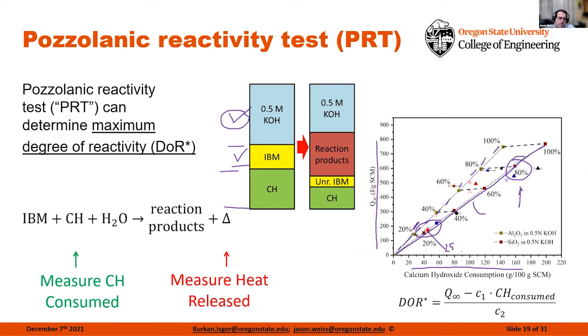There are lots of people who want to say, well, it's about the amorphous or glass content. This, for example, where you fall on this graph, and we've shown this before, is a great indicator of your glass or amorphous content. There's lots of other people who want to say, well, what if you have some calcium? We've got equations that account for these. And in fact, in January in Concrete International, we're going to have an article that really says you could greatly simplify a lot of the testing that we do for fly ashes simply by measuring the heat and using a graph like we see on the right-hand side. So this is something we believe in very strongly. We've presented it to ASTM. If they want to move it forward, great. If they want to continue debating other things, that's great as well. We're moving forward with this.